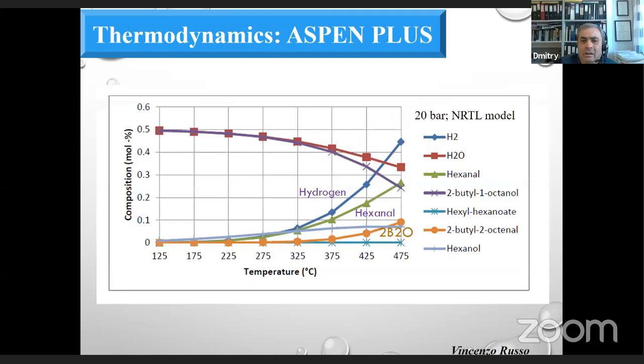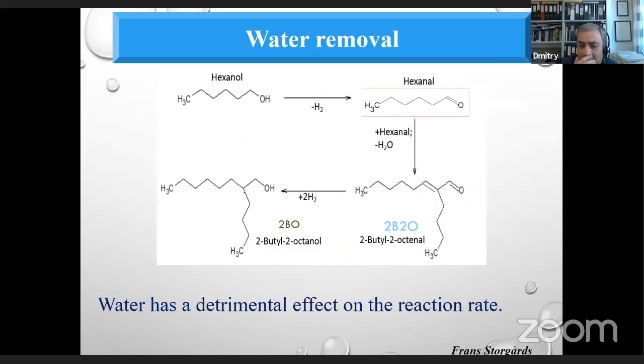product in 24 hours. So then we started to think about thermodynamics and made some thermodynamic calculations. These calculations were done by our collaborator from the University of Naples in Italy. He calculated the equilibrium composition dependent on temperature, and it seems that there are very strong thermodynamic limitations. So at least according to the calculations that we made, the maximum yield of the desired product, butyl octanol, would be just 10% or something like that.